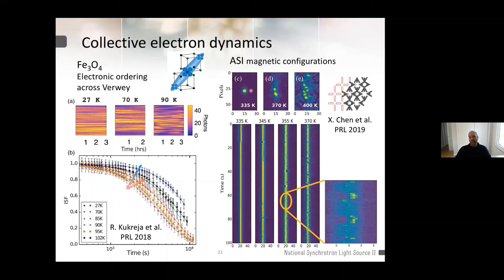And you can have a transition temperature that is tuned around ambient or even above, as was the case here. And you see that you get a magnetic signal that, going closer to the transition temperature, develops defects in the order. And indeed, you see speckles that are not present here and start to be present here due to the fact that you're visualizing the defects in the order. This can be done over time, as I showed before, with a waterfall plot. And you see that if temperature is small enough compared to the transition temperature, you have some kind of defect, but then essentially the situation is static all the time.